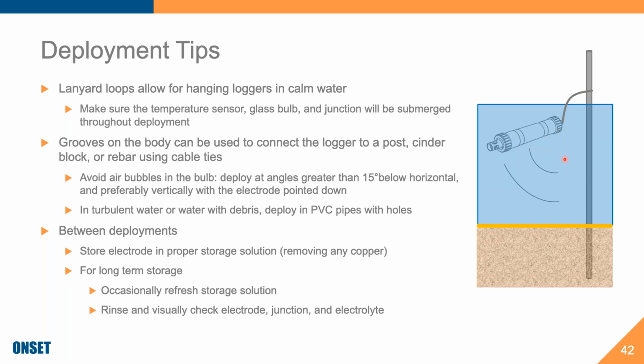So this is a nice way to hang your pH data logger or multi-parameter sondes if you're in water that is calm, so like a lake. For instance, this pH data logger was actually deployed in moving water. And so what we're finding is that the electrode is being moved rather close to the surface. It may not be submerged if this were a river, for instance. And you just want to make sure that when you deploy your logger, you have your temperature sensor, your glass bulb, and junction submerged throughout the deployment.